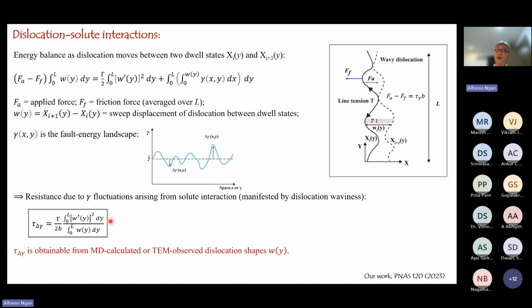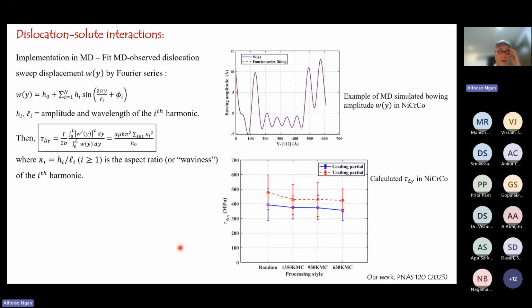So this equation is quite general. It doesn't involve any strong assumptions, just this energy balance, which should be correct. So what is needed would be this W(y), right? Which is the difference between the shapes in the two dwell states. And then we can obtain this W(y) from either MD simulation or from direct TEM observation. Of course, we need input from other results to be able to do the calculation. So for example, from MD, we can obtain a wavy dislocation. Let's say we can do a Fourier series fit to the dislocation shape.